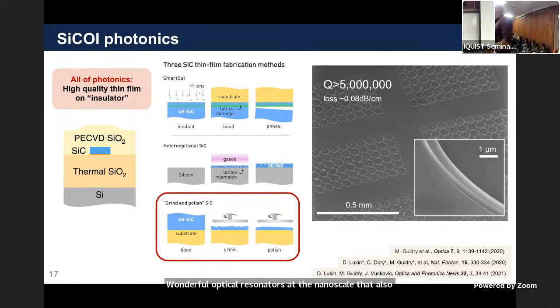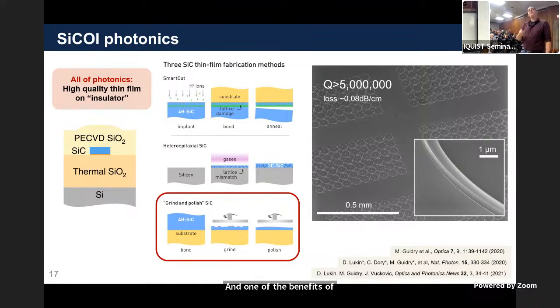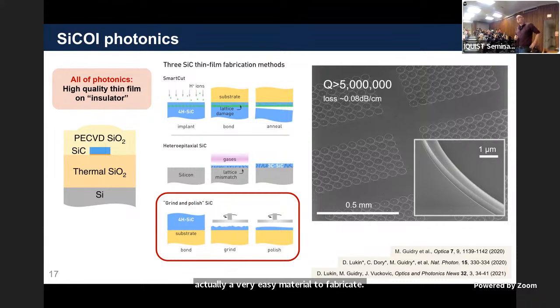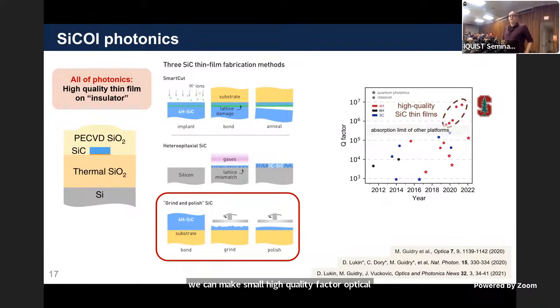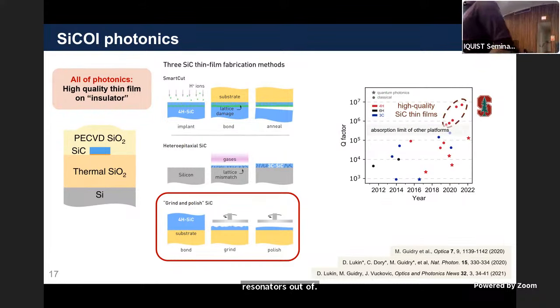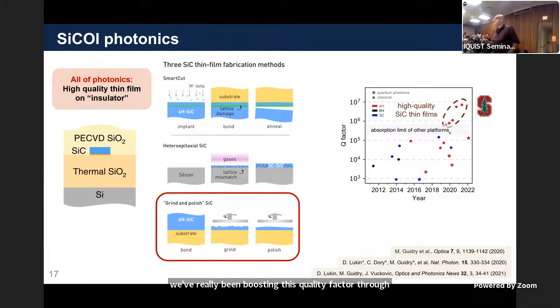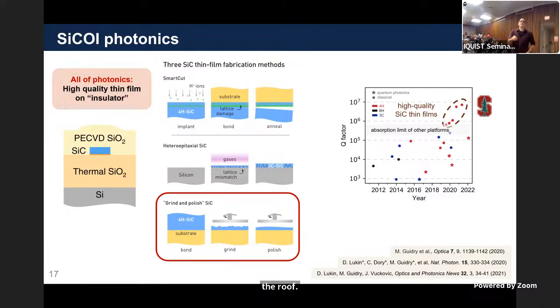One of the benefits of silicon carbide is that it's actually a very easy material to fabricate. So we've been able to make optical resonators with quality factors over 5 million with extremely low loss. For those fab people in the audience, the sidewalls look really great. So it's an easy to fabricate material that we can make small, high quality factor optical resonators out of. Over the past 3 years or so at Stanford, we've really been boosting this quality factor through the roof, through improvements in materials and fabrication. So now we're having almost 10 million quality factors, which is great.